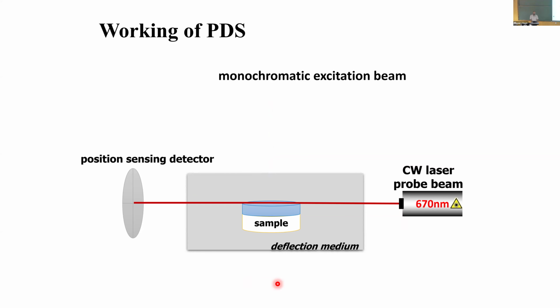In this case, what we do is this absorption would lead to non-radiative decay in some way, and that will lead to some heating in the sample. So that heat is what I have to measure. Now, if I had a sensitive thermometer to measure that slight variation in heat compared to room temperature, I've used that. But I don't have such a sensitive thermometer because the heat I'm trying to measure is in nanokelvin to microkelvin range. It's very small.